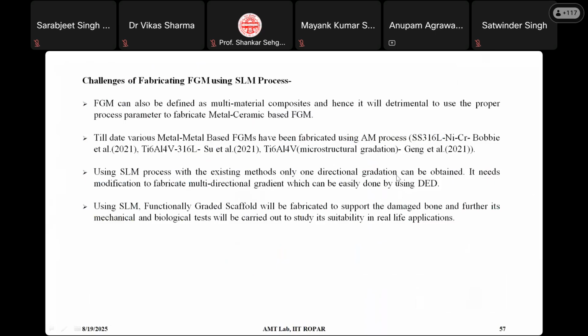Now using the SLM process with the existing method, we can have only one directional gradation, maybe some gradation in the structure, but not multi-directional gradients processed with the correct set of parameters. We can predict that for each point in the material we should have the laser intensity at some specified value, but having that facility available in the machine is something which is not yet there. Using simulation techniques we are able to find the ideal parameters, but we are not able to give those parameters using the machines that we have. So this kind of facility is very much required.